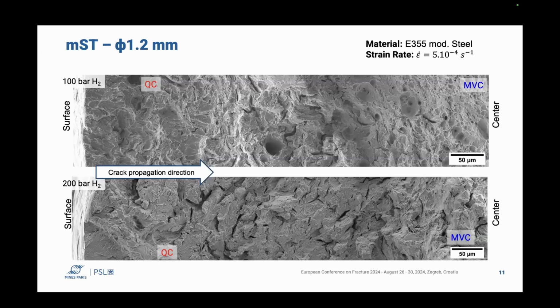And when we compare with 200 bar, we can see that we have the quasi cleavage feature in almost all of the fracture. But if we pay attention here, we can see very, very small dimples that are even smaller than the dimples at 100 bar.